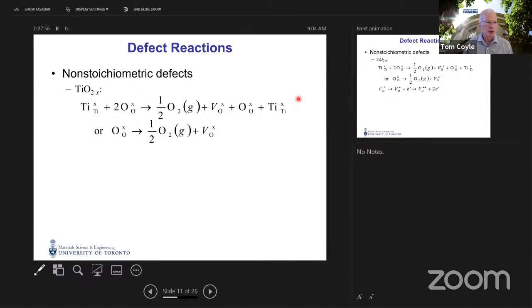Given that this Ti on a titanium site isn't involved in the overall reaction, and one of the oxygen on the oxygen site is not involved in the overall reaction, as in normal chemical reactions, sometimes it's convenient to leave those species that don't really participate in the reaction out of the equation. And so we can simplify the equation by focusing on that oxygen atom, which in fact does leave, creating a vacancy and creating half an oxygen molecule.